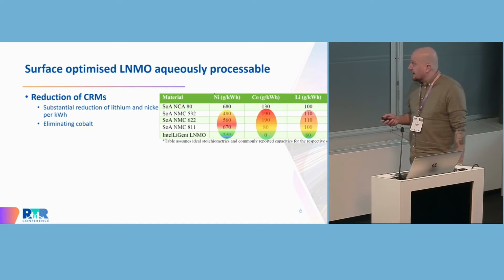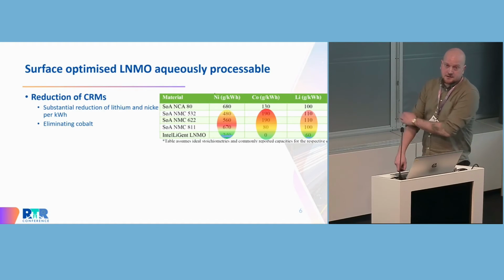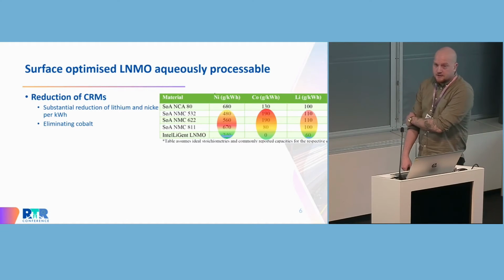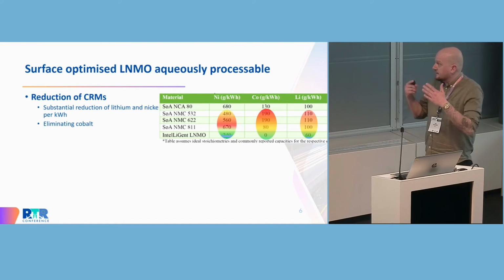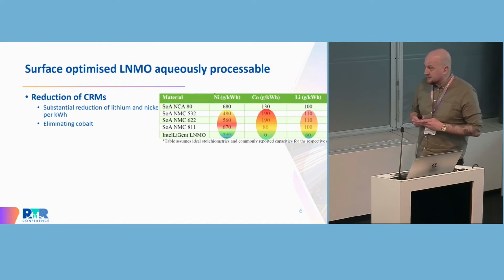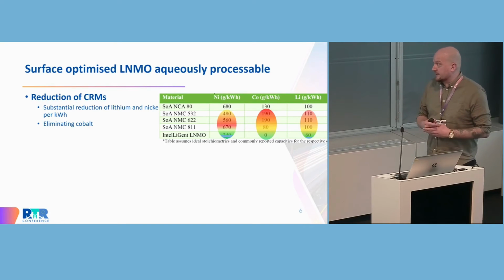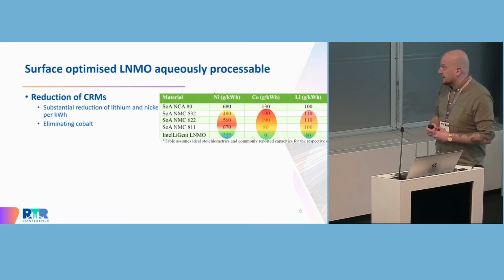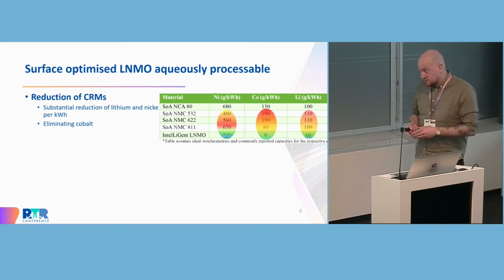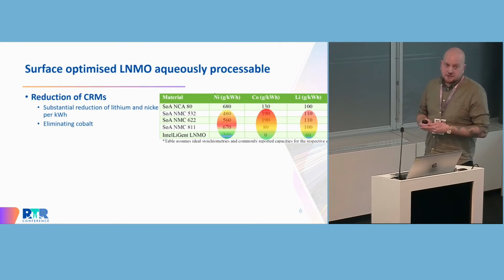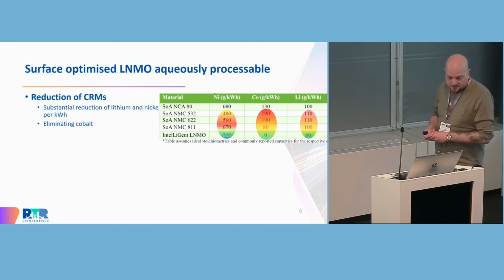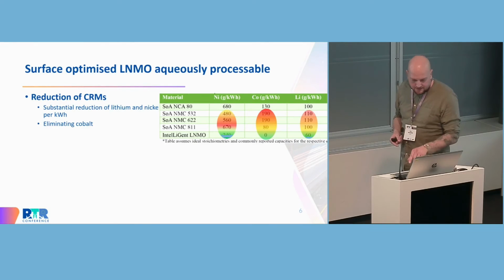But also to highlight that our lithium content in grams per kilowatt hour is lower. So this is due to the fact that LNMO is a spinel structure, which in comparison to layered oxides can be completely delithiated and relithiated in every cycle. So in layered oxides that Jordi and also Ruben already presented to you, we have what we call structural lithium that will stay in the structure. We need that for stability. The spinel is a framework and doesn't require that.